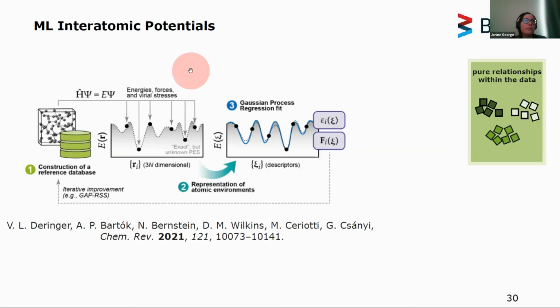There we've used machine learning interatomic potentials to simulate phononic properties. So what you do is you use a large reference database, typically from DFT data, that has information on energies and forces. And that you learn with a certain representation of the atomic environment and nothing else, and a certain type of regression algorithm, and then you learn these energies and forces.